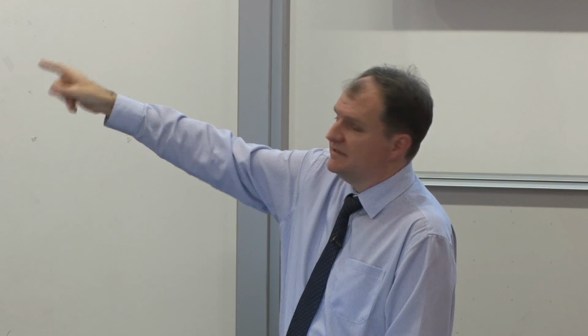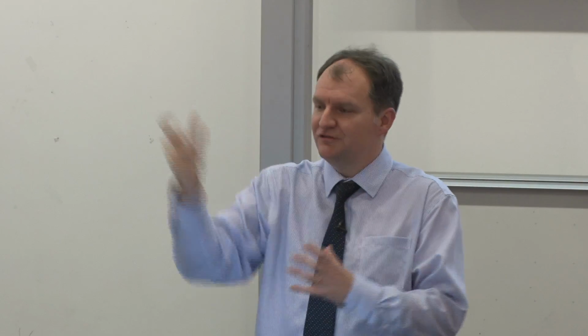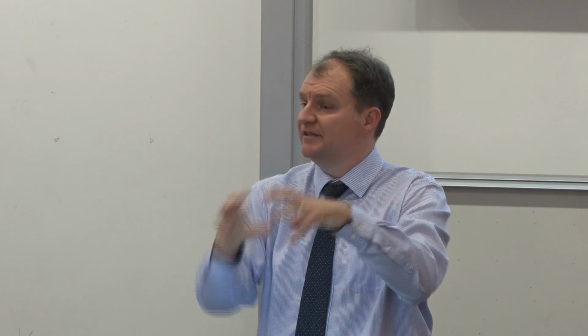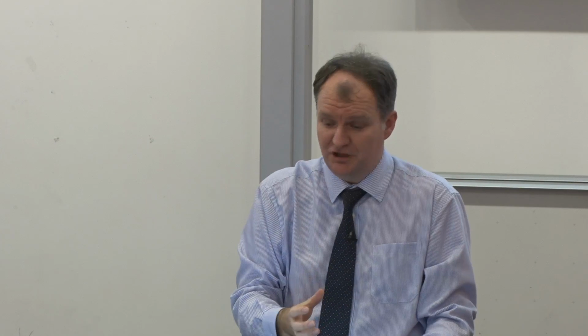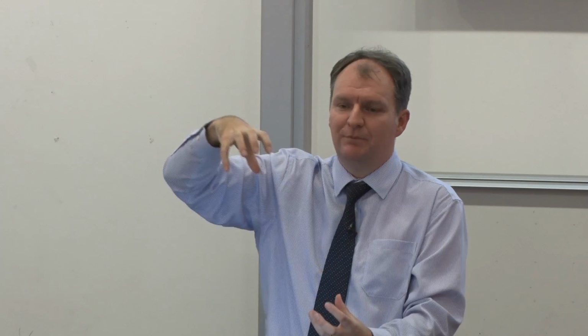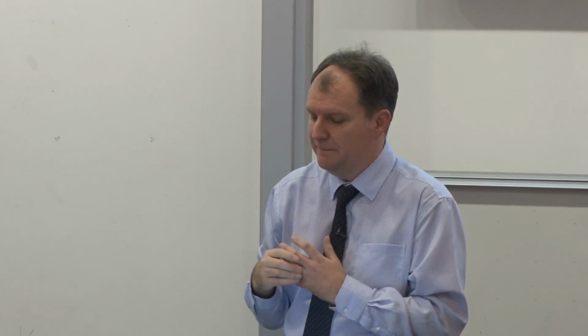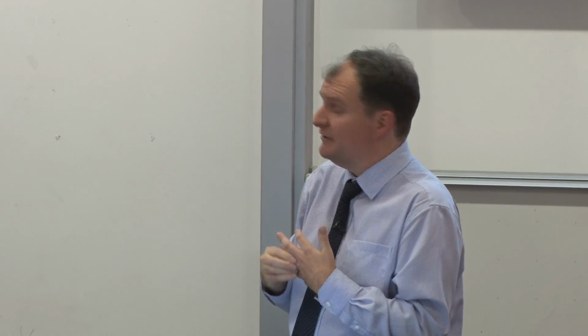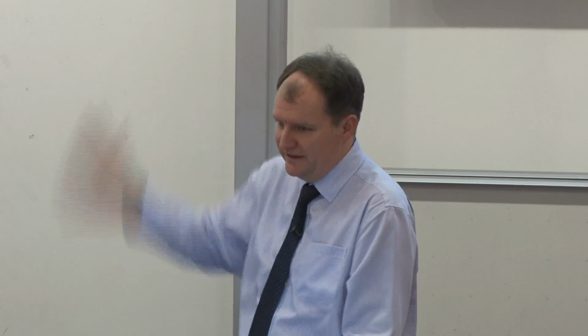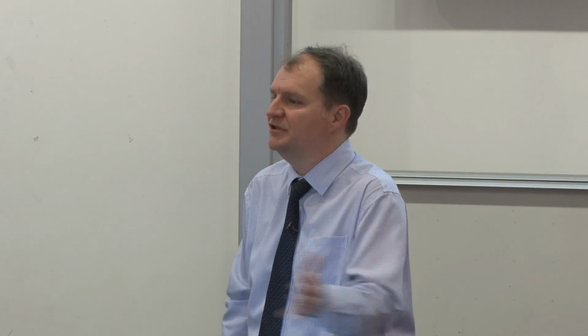But at 2 millimeters, you get something which is completely dominated by capillarity. So basically, your flow structure is trying to minimize its surface area. So the shape it forms is to do with surface tension. You still get flow down it through gravity, but the shape of the flow path is capillary dominated. You go up to 2 centimeters, and capillarity still plays a role, but suddenly things are orientating themselves with gravity. So you're getting this change in your flow behavior over the sort of range of particle sizes you get in heap leaching, which of course is a challenge for predicting this, which the industry won't like, but from an academic side, of course, it does make it something interesting to study.